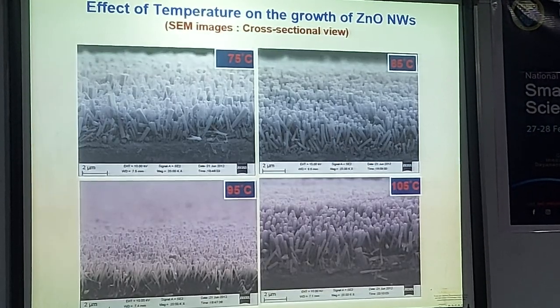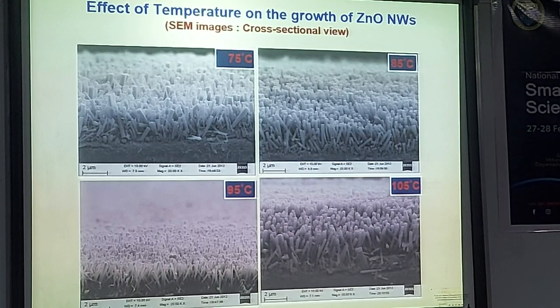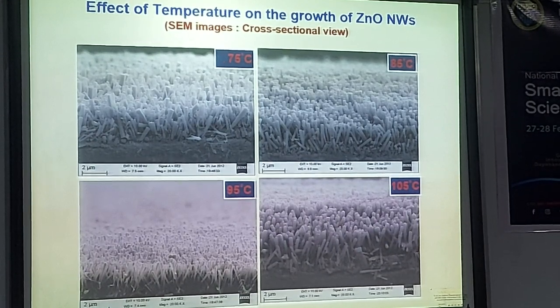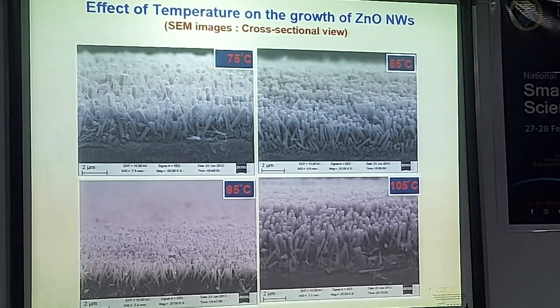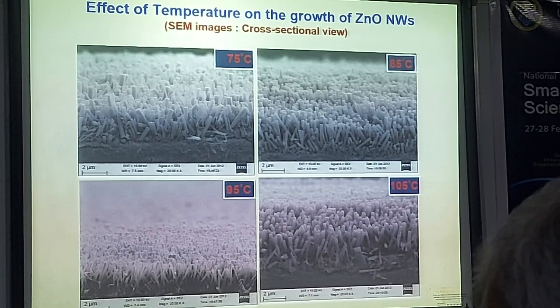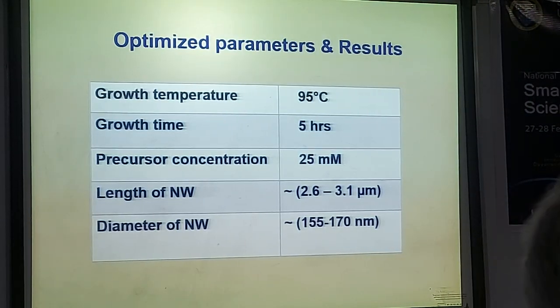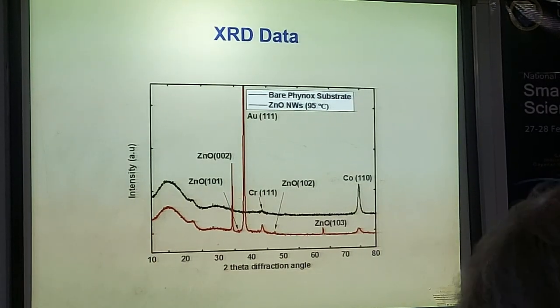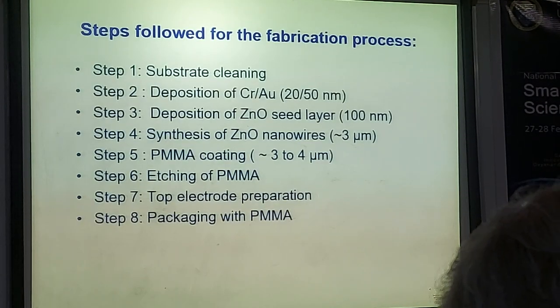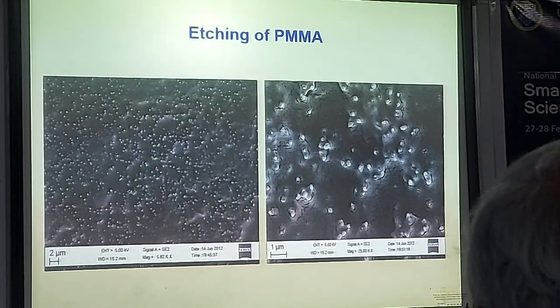Some more data on the size and the length of the nanorods that we could get, from electron microscopy pictures. There are various parameters we can optimize to get the required size of the zinc oxide nanorods. So these are some of the optimized parameters. We analyzed using XRD and other techniques. And we have used these zinc oxide nanorods to fabricate a nanogenerator.